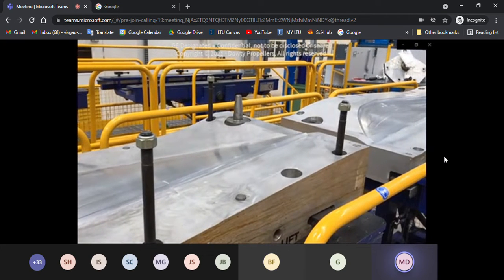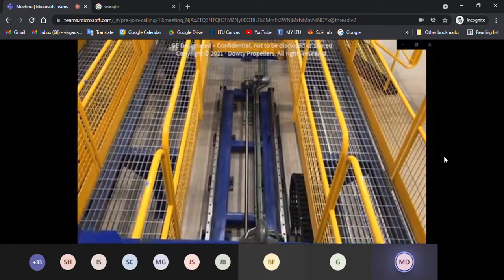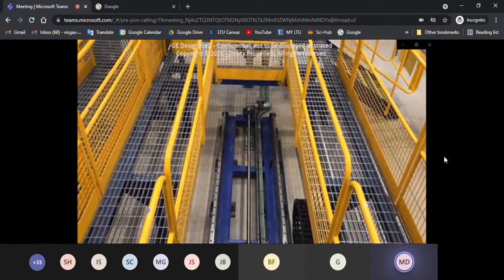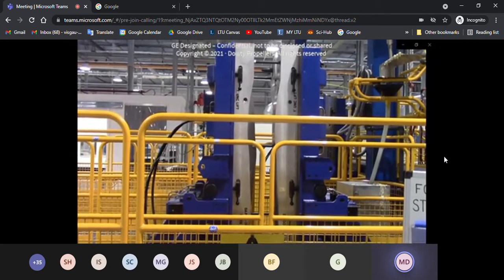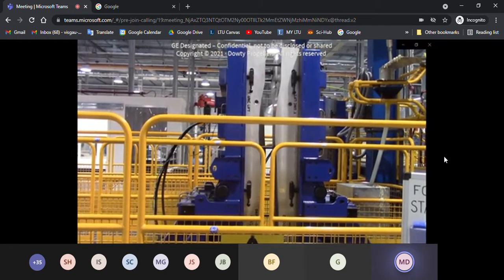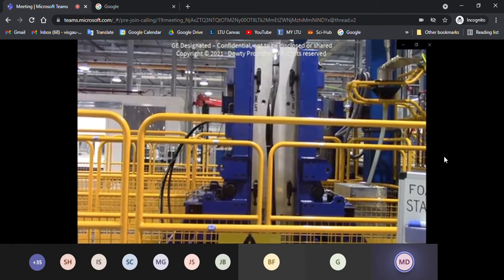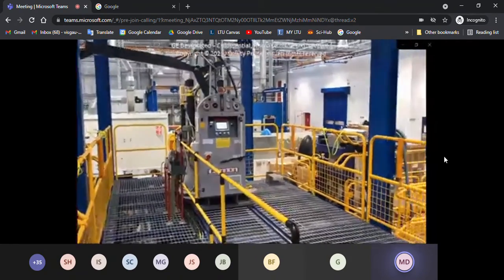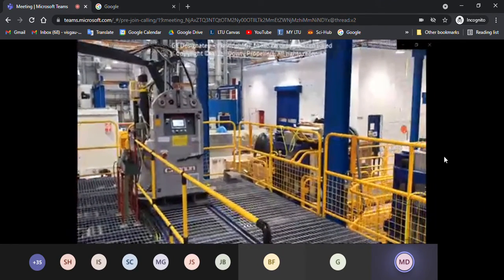This is a clamshell mold and it's hydraulically actuated, so once the preforms have been placed inside and a special treatment is applied to ensure that the foam bonds well to the composite, the 2 halves of the mold are closed together. This is all automated. So after the operator has inserted the preform, the machine takes care of the rest. The 2 halves of the mold are brought together, and the preform is heated and prepared and pressurized, ready for the foam injection machine here to be brought over and inject a pre-mixed foam mixture into the mold.